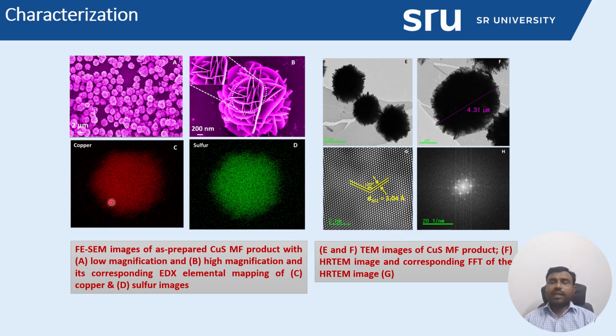So the simple reaction for the formation of this copper sulfide morphology: we did not use any template, either hard template or surfactant or polymeric material. We did not apply any of these to achieve this process. We simply use a copper precursor and sulfur powder as a sulfur precursor in ethanol. So all are green approaches. And also we apply a moderate temperature to achieve this product. So the hydrothermal process is beneficial for the highly uniform synthesis of this copper sulfide microflower.